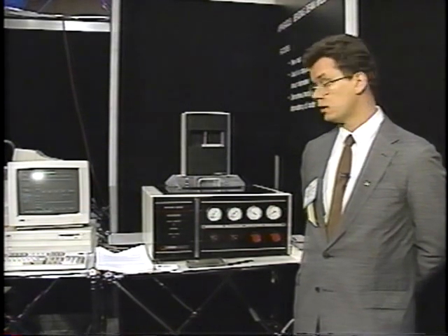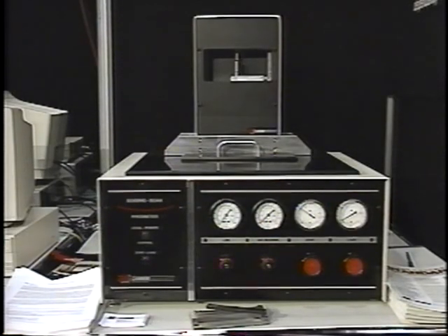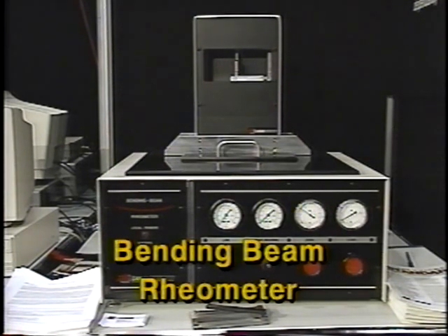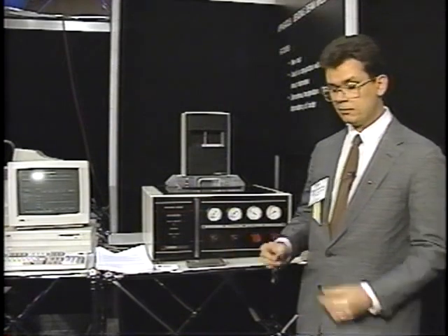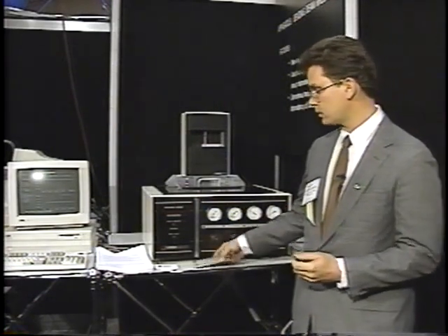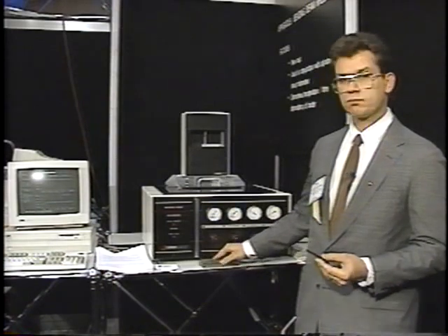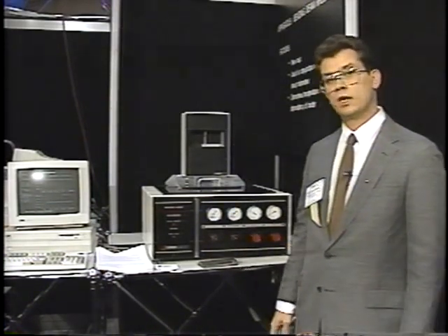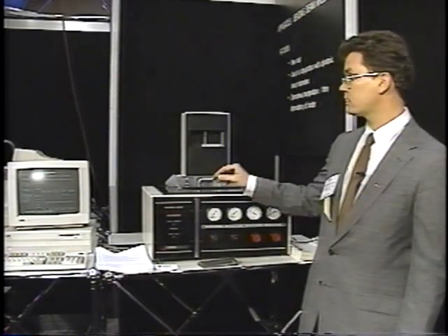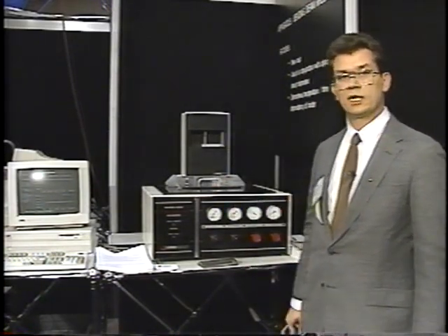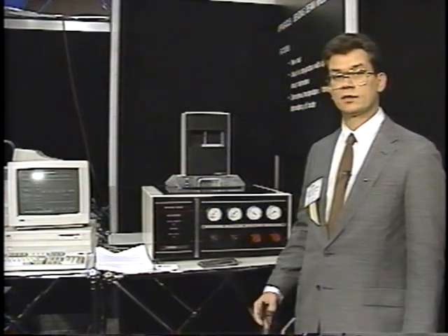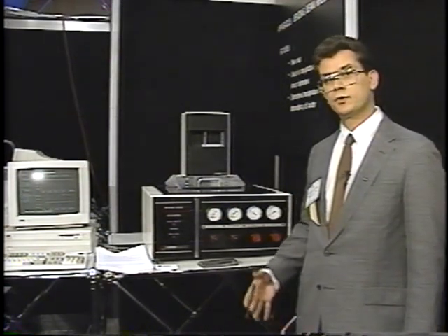This is the second proposed SHRP specification test on asphalt cement. What you see behind me is the bending beam rheometer, developed at Penn State and now available commercially. In this test we take a small beam of asphalt prepared using a mold like this. The beam is placed in this device in a bath cooled to about -15 degrees C. A load is applied up here which bends the beam, the deflection is measured, and from that we calculate the stiffness at low temperature, which is a good indicator of low temperature cracking. Low temperature cracking is a big problem in the northern U.S. and Canada, and through this test we hope to eliminate this problem from our roads.